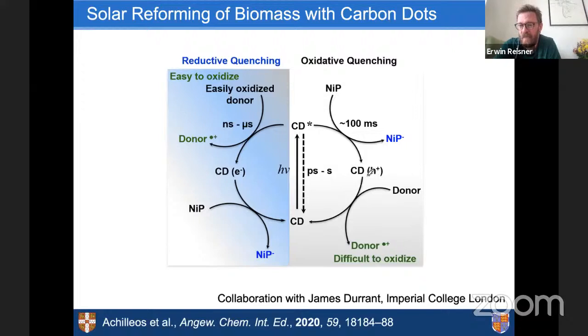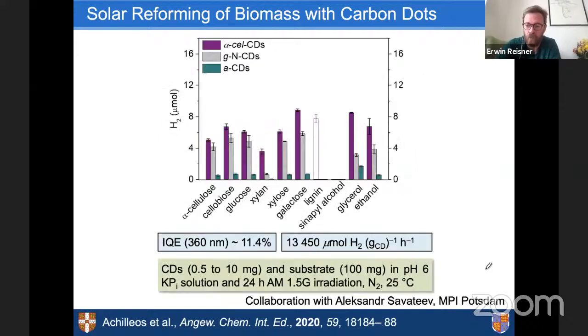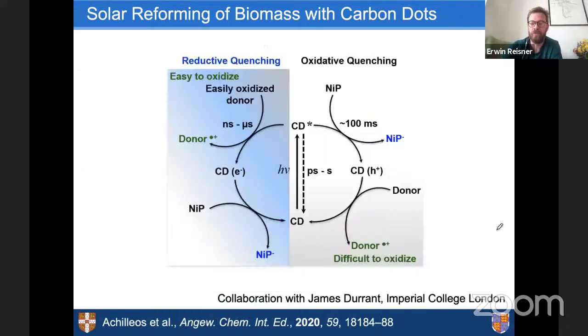So this oxidative quenching, we don't have definite proof, but I believe this is really essential to access these difficult insoluble substrates. And once we have partially broken them down, we can actually go through the much quicker reductive quenching pathway and accelerate our hydrogen production much more. So there are some kinetic tricks here enabled by two quenching pathways in the system. And this was a collaboration with James Durrant. I should have mentioned before, this was also a collaboration with the Max Planck Institute from Antonietti, with Aleksandr Savateev here, who did some of the analysis for us.